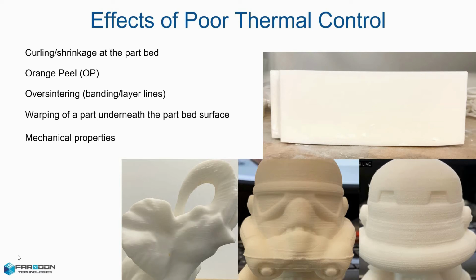Next, we have warping of a part underneath the part bed surface, usually seen during the post-processing stage known as part breakout, when a part is visibly warped once placed on a flat surface or visually inspected. This can be due to insufficient cooldown times, either in the machine after a build or out of the machine in ambient cooldown. A 1-to-1 build cooldown scale is recommended for ambient cooldown. Once the internal temperature of the build is at least 85 degrees Celsius, then it is safe to break out the parts. If the recommended cooldown procedures are followed and parts are still warped, then the part piston heater and/or cylinder heaters need to be increased.